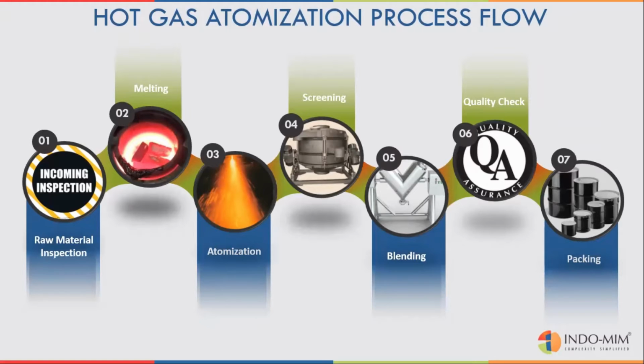The very important step is selection of raw material. You may be aware that in the vacuum melting process, the melting and everything happens in a closed chamber. So there is no possibility for us to upgrade the material quality. It has to be controlled from the raw material side. So the chemical composition, the trace elements and any of the gaseous content must all be controlled in the raw material. That is the most important aspect of this process. Then there is the melting process. It happens in vacuum, or it may also happen in a protective atmosphere, either nitrogen or argon. Depending on the product, we will select it.